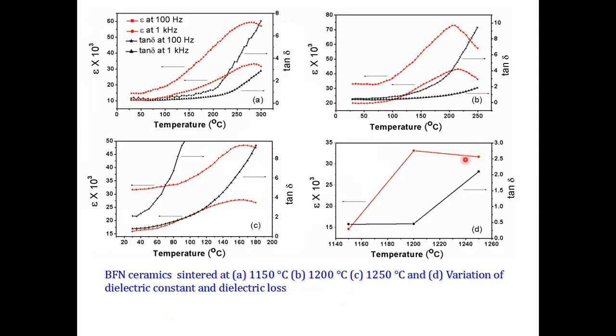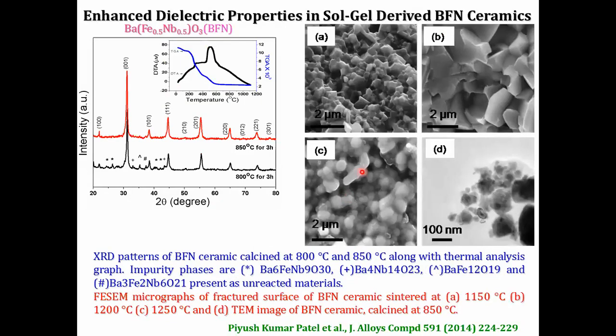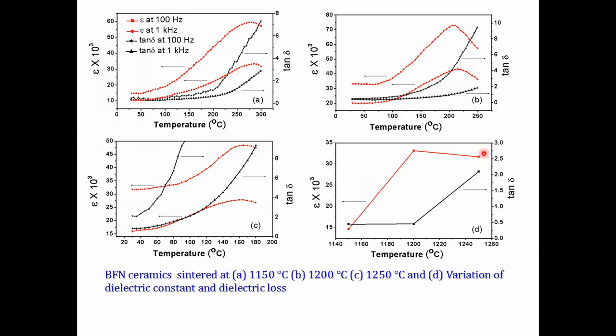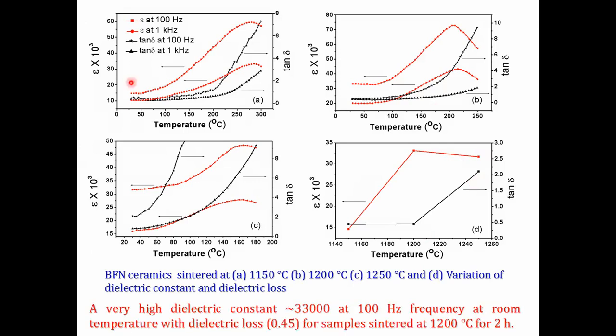That is the effect when it just reaches 1250, it has melted, and so the dielectric constant has decreased and loss has increased here. So you can see that heating at 1200 gives a very high dielectric constant of around 33,000 at 100 Hertz frequency at room temperature, with a dielectric loss of 0.45 for the samples. So this is the best temperature at which you can heat it.